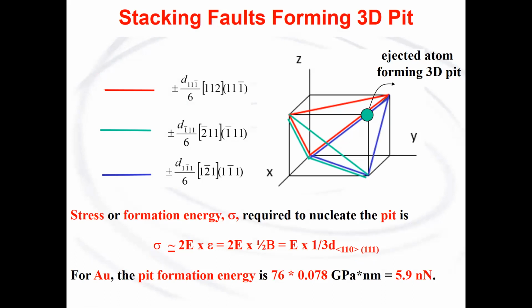The stress or formation energy thus required to nucleate the pit is 1/2 the energy of the dislocation. So the formation energy sigma is approximately 2 times the elastic modulus times the strain. And the strain for the relaxation is 1/2 times the Burgers vector. And as a result, it's just the elastic modulus times 1/3 times the interatomic spacing, the 111 spacing. And when we calculate this, the elastic modulus is 76 gigapascals, and the strain is 0.078, and it gives a formation energy of 5.9 nanonewtons.